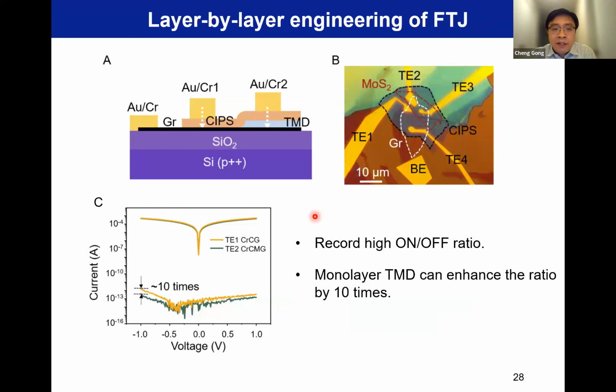So for such a ferroelectric tunnel junction, we routinely demonstrate a 10^9 on-off ratio when we polarize the ferroelectric layers; the resistance is changed by 9 orders of magnitude. And sometimes I encourage students to try putting in just one layer of TMD, which is also a gapped system, and see what happens there. Sometimes they observe a 10^10 on-off ratio. So in order to prove this is true, rather than sample variance, we designed a well-controlled experiment.